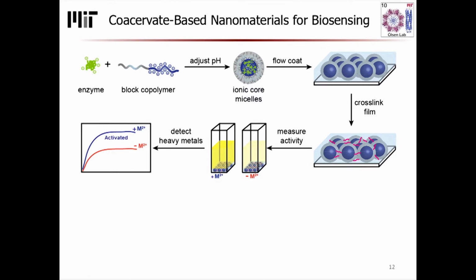When you mix the protein and the block copolymer in solution, if the electrostatics of the system is controlled correctly, this will self-assemble into ionic core micelles. Basically, block copolymer micelles in solution, where self-assembly is driven by charge. You can then coat this into nanostructured films, and you can use this charged copolymer to control the structure, distribution, and presentation of the protein. In particular, you can use it to stabilize and maintain the dispersion of the protein in the solid film and allow you to produce a material of interest.